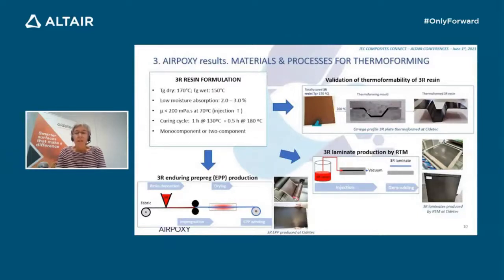Once the resin was formulated, its thermoformability was validated, and for that, a resin plate fully cured with a Tg of 170 degrees was successfully thermoformed at 200 degrees, as you can see in the picture. Once the thermoformability of the resin was confirmed, fully cured 3R laminates were produced using the resin transfer molding process. On the other hand, enduring prepreg was also produced.